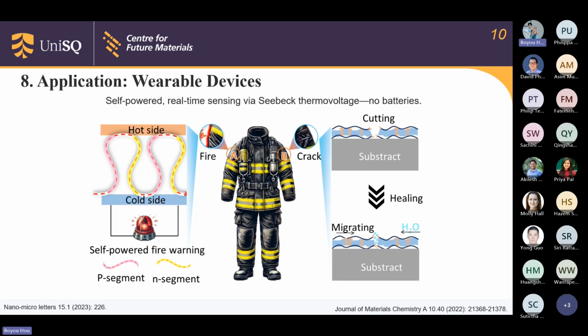If the coating is cut or cracked, mobile groups in the polymer and a little moisture from the air migrate to the damaged zone. They form new hydrogen bonds, so the electrical path reconnects and the warning function returns without replacing the patch. The healing can repeat for several cycles, depending on the humidity and the temperature.